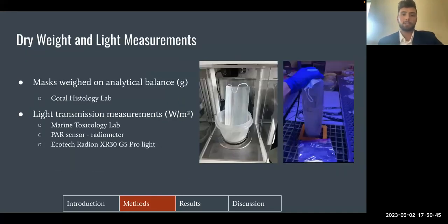So this part of the experimental procedure is where we gathered the most simple bits of data. After the masks dried after each sampling day, they were first taken up to the coral histology lab and placed in an analytical balance, which measured their weight in grams. Weight measurements were taken before the masks were exposed to the experimental conditions. After that, they were taken back down to the marine toxicology lab, where they were placed over a sensor that measured photosynthetically active radiation, or PAR, under an LED light.